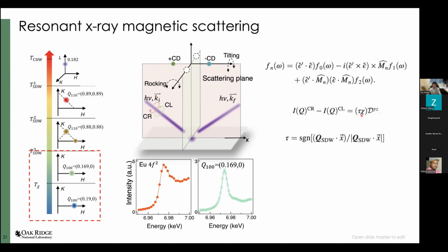So let me explain here a little bit more. Assume you have a single domain helical spin density wave. You're going to see circular dichroism. But if you look at the positive Q and check your circular dichroism, it will be negative. And once you go to the negative wave vector, it will be positive. So the sign would be different. It naturally arises from this formula. So this would be a key signature to use resonant X-ray magnetic scattering to distinguish a helical spin density wave.